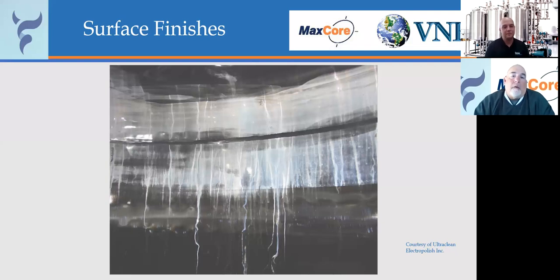To be honest with you, I'm glad you brought that up, because one of the things that we've done at BPE is we've acknowledged the fact that because of the high nickel from the weld insert rings, you may have some weld dross and colored splotching on the surface in those welds. We've actually gone in and addressed that in BPE, because we do know it's one of the byproducts of using these high nickel alloys when it comes to over alloying. It is there, and as long as you can explain it to your customer and point them in the direction of that issue, it's pretty well acceptable.